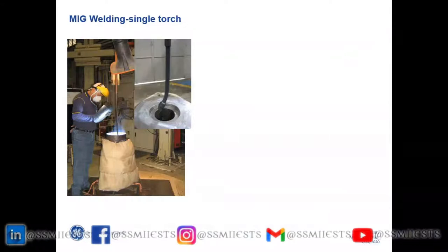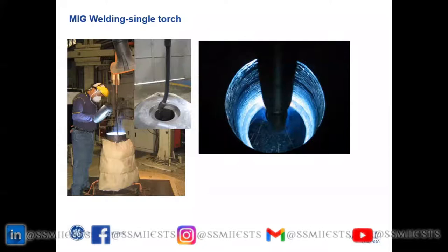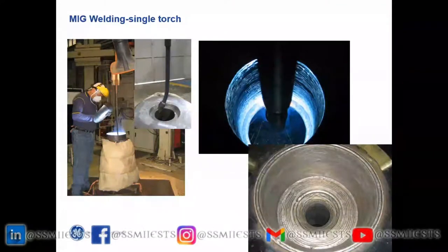So this is like a torch, and wire will be coming, and those areas will be filled up by the cladding material. It is a very typical process, very specialized, because we don't want the iron to come to the surface, right? Because if the iron comes, it will start corrosion again. So the purpose of cladding is to reduce the iron dilution on the top surface. We put a layer of 5 mm, and then we machine it out, because we need a very, very good metal-to-metal seal. So we'll take out 2 mm, leaving a 3 mm minimum layer, and the iron dilution should be as minimum as possible, right?